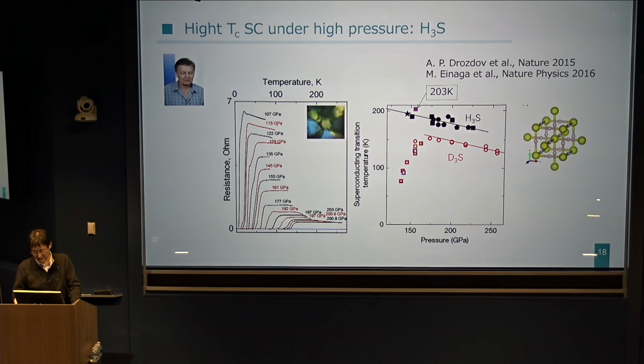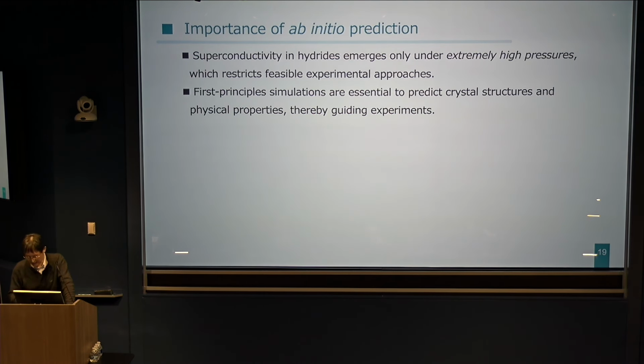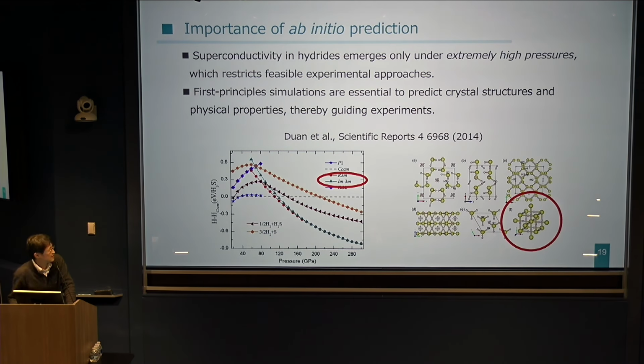But it should be noted that this is a very interesting and remarkable experimental discovery. But here I'd like to note that just 5 weeks before this experimental report, Duan and others posted a paper predicting that when we apply very high pressure, hydrogen sulfide becomes H3S, whose crystal structure is shown here, and it is very good for superconductivity. So this paper indicates the important role of ab initio calculations.